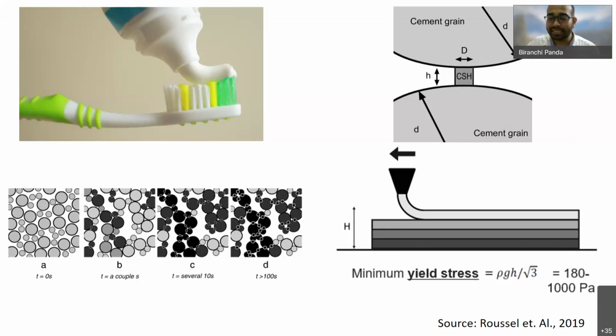So can we get this yield stress if we use cement, which is very commonly used in the construction process? Yes, it is possible. If you look into the mechanism, this is explained with respect to time. What happens once you add water to cement particles? They try to flocculate. They come together because they have van der Waals forces of attraction. And also with time, C-S-H particles get formed, and they also bind the cement particles. So in this way, with time, the cement particles flocculate.